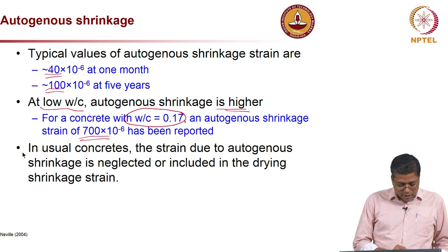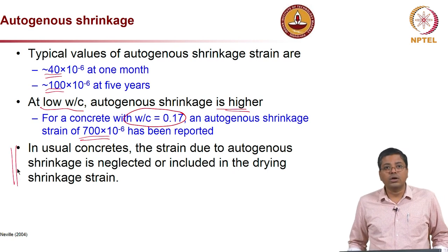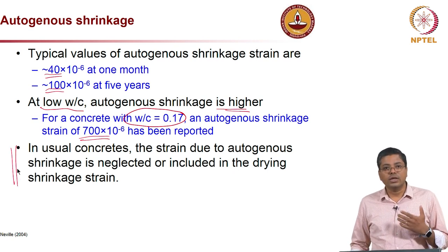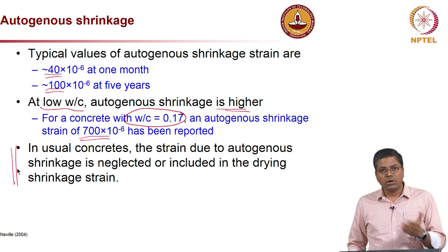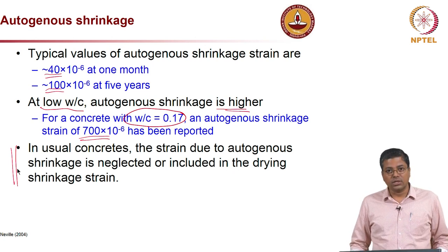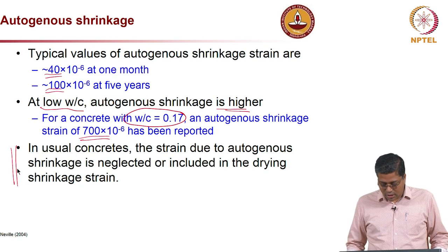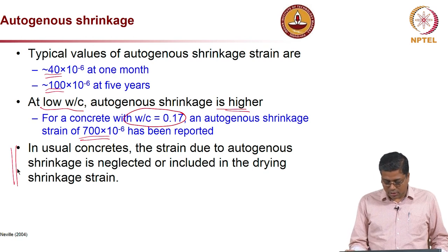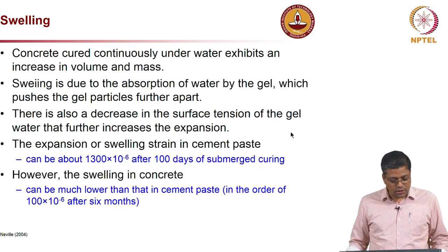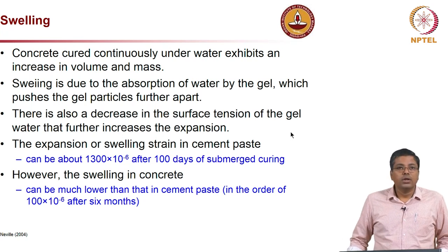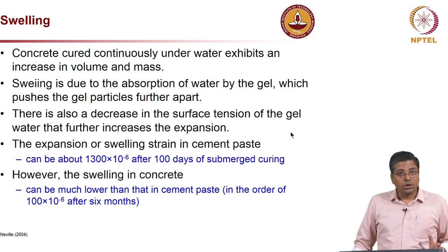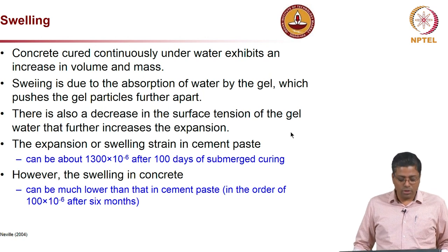But usually when you talk about concrete, autogenous shrinkage is usually neglected or it is included as part of the drying shrinkage strain because of the difficulties in the measurement. So, total shrinkage is what is reported usually. Now, swelling, concrete also swells when it is exposed continuously to water.